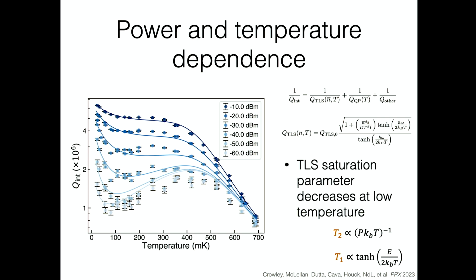But what I'm going to assert is, okay, I can write down a model for what this quality factor should look like as a function of temperature and power. And there are some mechanisms that are temperature and power dependent. There are some mechanisms that are not power dependent, but only temperature dependent. And then there are other mechanisms that are temperature and power independent. So I can now sort of sort everything into being dependent on these two different parameters.